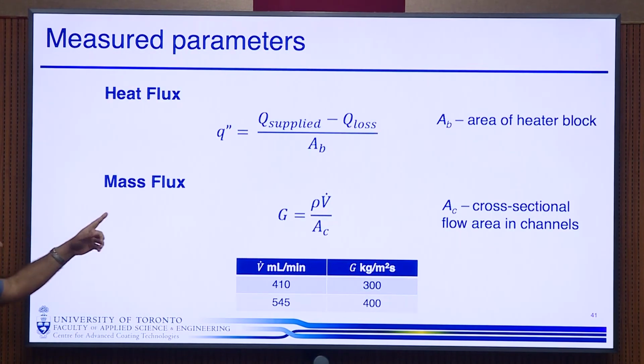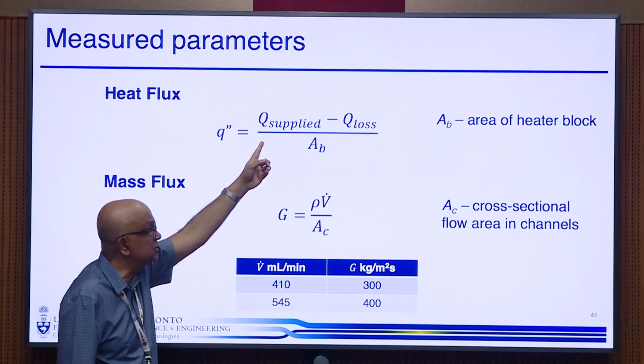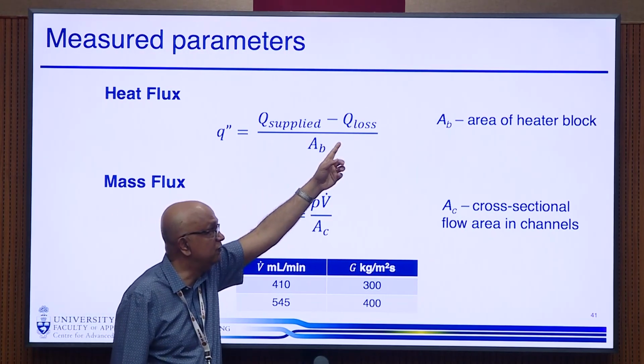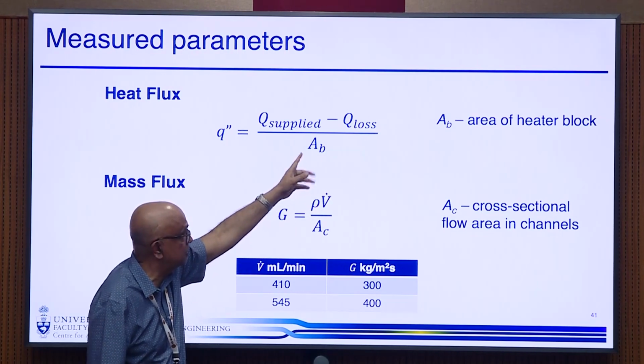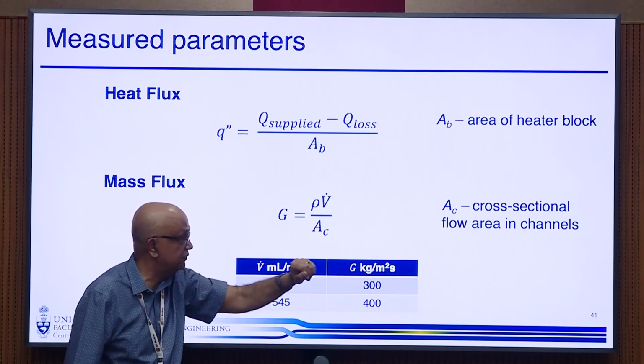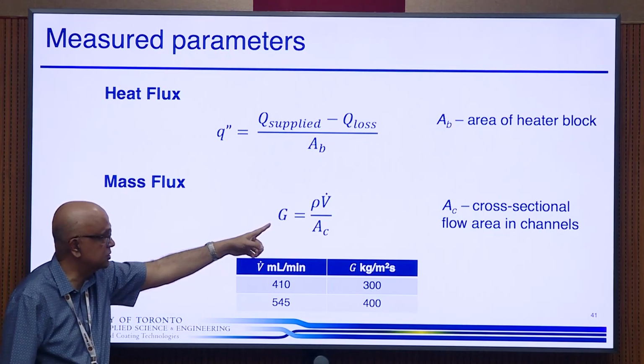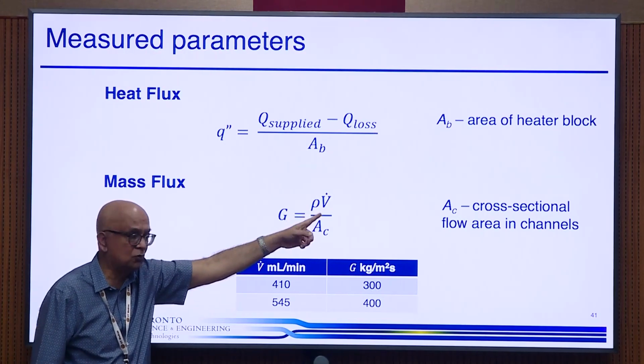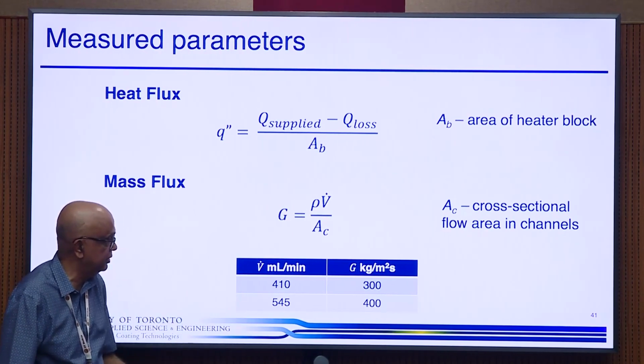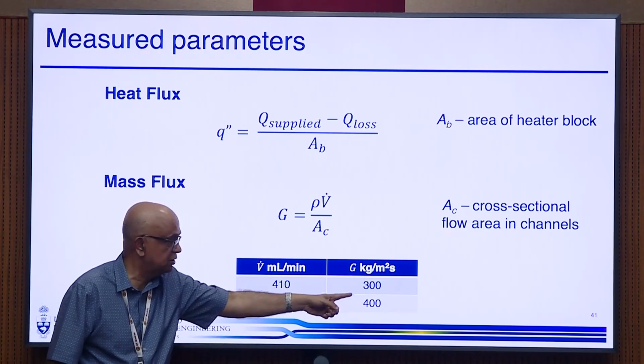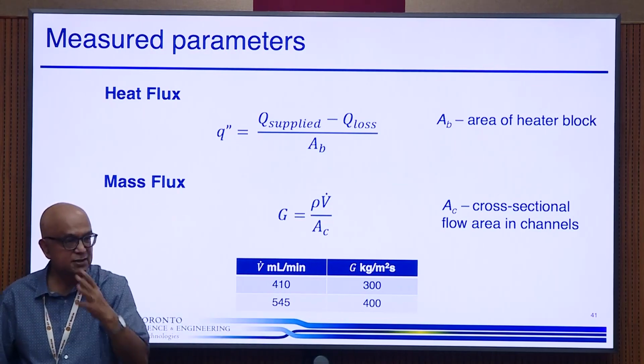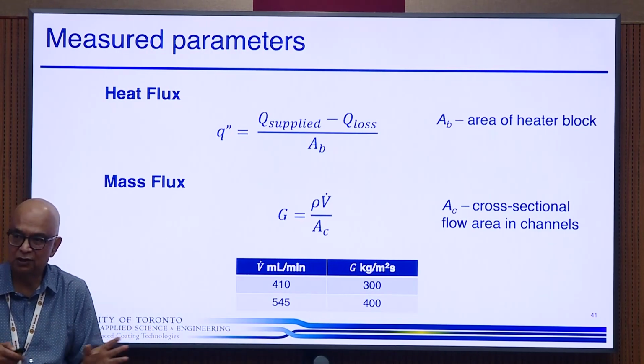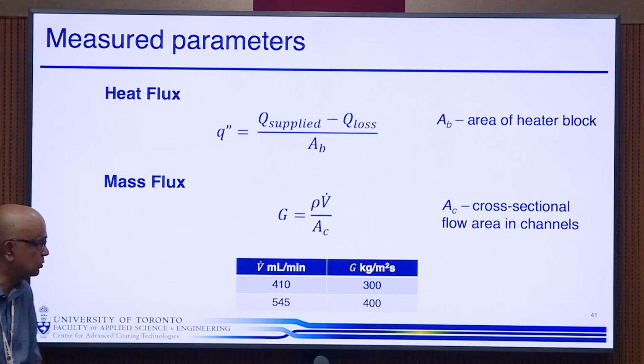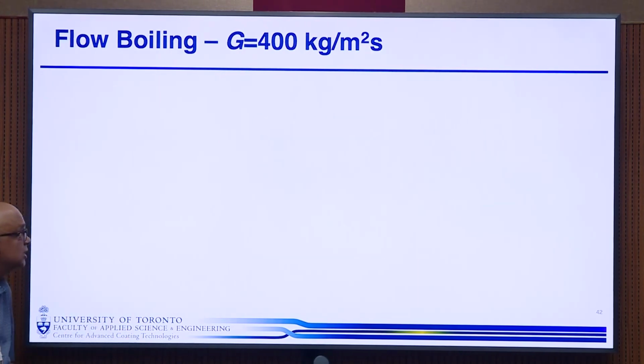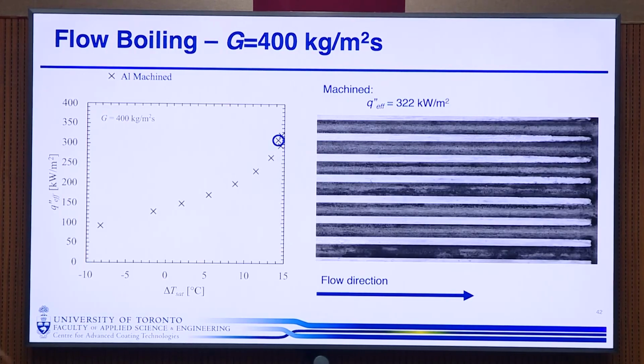So we are measuring the heat flux. The heat flux is the electrical energy supplied. We are losing about 10%, so we subtract that, divide that by the area of the heater block. That's our heat flux. This is the mass flux. So we are taking the total mass flux of water going through, dividing by the cross-sectional area. And I'll show you results at 300 and 400 kg per meter square second, which, you'll find in the literature, is about the mass flux people tested at.